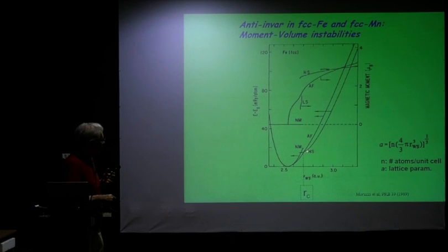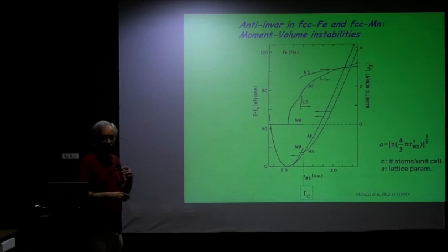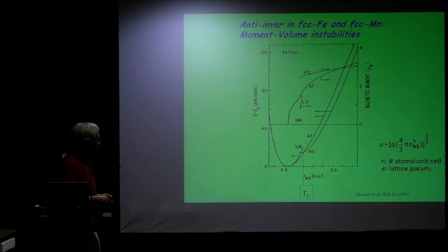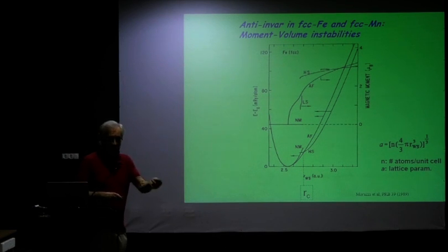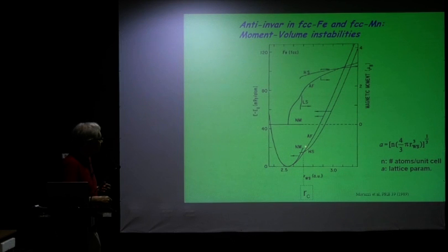The magnetic moment of the ferromagnetic state below this critical value is practically zero, and then you have stable solutions over here, which are referred to as a low spin state, and then it jumps up, and then you go into the high spin state. So the ferromagnetic state is not a unique state, but it has a low spin state and a high spin state. And under equilibrium conditions at very low temperatures, the antiferromagnetic state of Fcc iron should be the stable state. And as you go to higher volumes, you have the high spin state as a stable state.